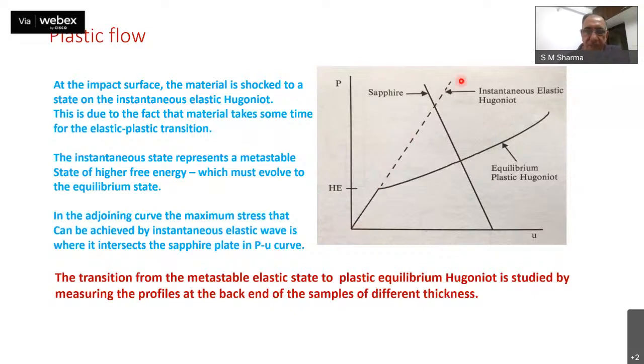Specifically, what is going to happen, I'm showing here. This is a PU diagram, if you recall. The PU diagram of an elastic material, for example, is this, shown extended by a dotted line, which is this. But in reality, beyond a certain threshold value, which we call the Hugoniot elastic limit, beyond this it does not extend. It actually deviates from this particular value. So the PU curve, in the case of plastic flow, starts showing a feature like this. It increases elastically to a value and then it takes a different path. So we will call that the equilibrium plastic Hugoniot. In contrast, we call this the instantaneous elastic Hugoniot.